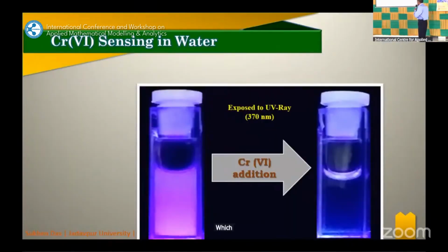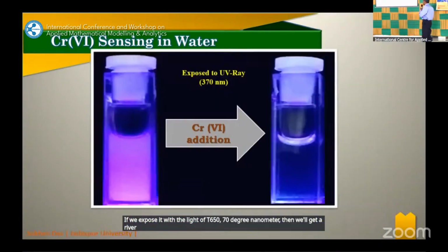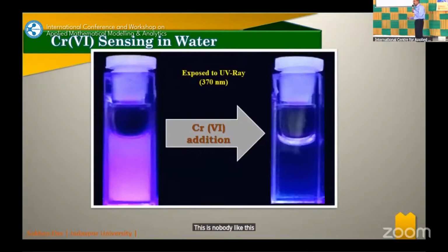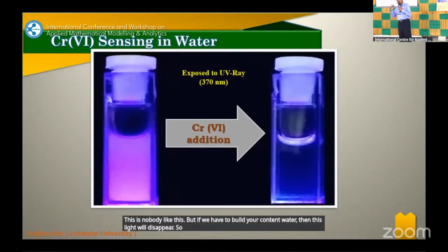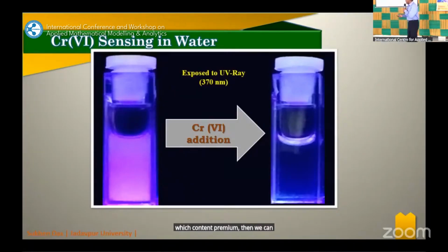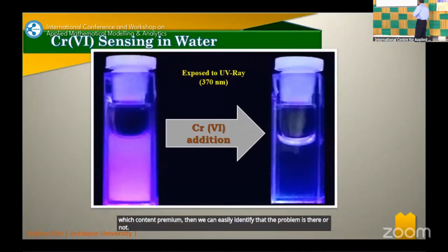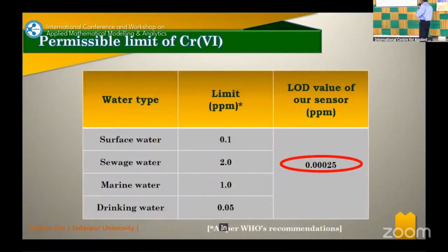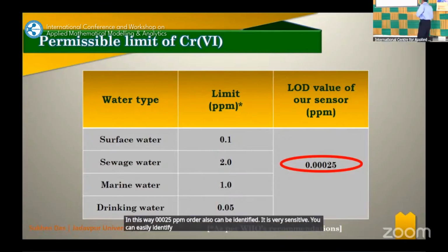Actually, if we expose it to light of 370 nanometer, then we'll get a reddish fluorescence property like this. But if we add chromium or chromium-containing water, then this light will disappear. So if we can find a device where this type of fluorescence property will be there, and we put one drop of water which contains chromium, then we can easily identify whether the chromium is there or not. So in this way, 0.00025 ppm order also can be identified. It is very sensitive.